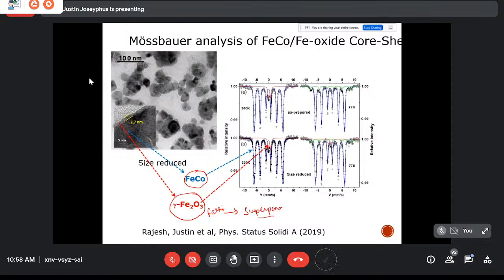So from the fraction, that is a doublet at room temperature, it is superparamagnetic, and when you go to 77 Kelvin, the doublet disappears. So that means it is more stable at low temperature. Okay, stable means magnetically, it is not fluctuating. So at 77 Kelvin, your double-line pattern becomes a 6-line pattern. So that means you have an iron cobalt core and a superparamagnetic oxide shell.